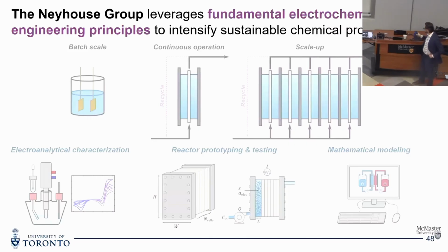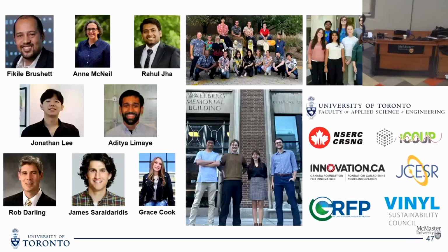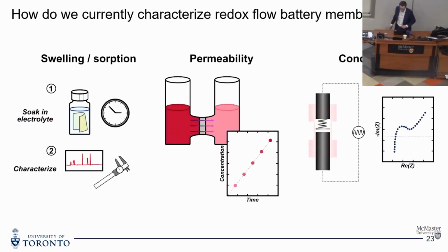I was just worried, I'm a dangerous chemist. I know not to get into trouble. But on slide 23, you showed that H curve and the concentration curve beside it. Now, I don't know if I'm thinking in terms of diffusion or osmosis, but shouldn't that have a curve that tapers off as the concentration changes? Yes. Eventually these are going to fully mix, and as the concentration gradient minimizes, this will eventually plateau. What this shows, and when you would take these measurements, is at the shortest time possible, where you can capture the behavior without dealing with that change in the driving force. Otherwise, it would take a little bit more modeling to get that right.